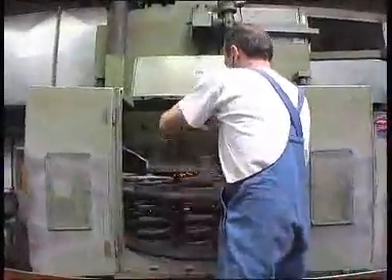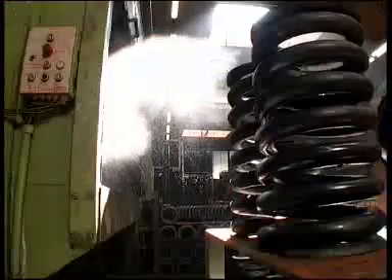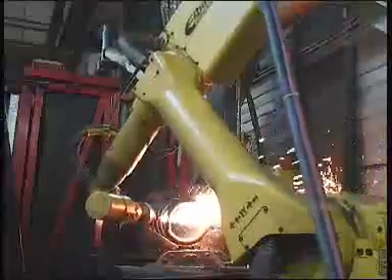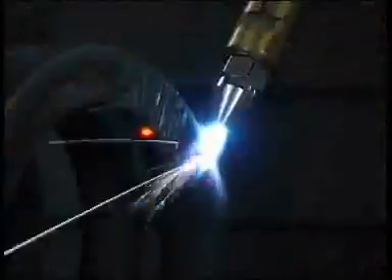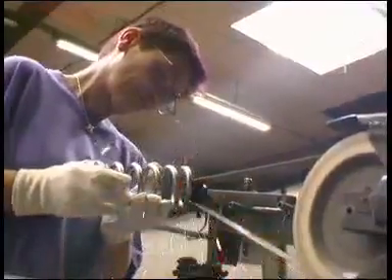Next, as a rule, comes the process of grinding the spring ends. This must be performed with the utmost accuracy in order to avoid any skewing of the spring ends — the prerequisite being end surfaces that are straight in relation to one another, and an accurately centered spring axis. Grinding is a very time-consuming process. In order to save time, large wire diameters are prepared by welding robots. After the grinding process, the sharp burrs are then removed according to your requirements and the edges chamfered.